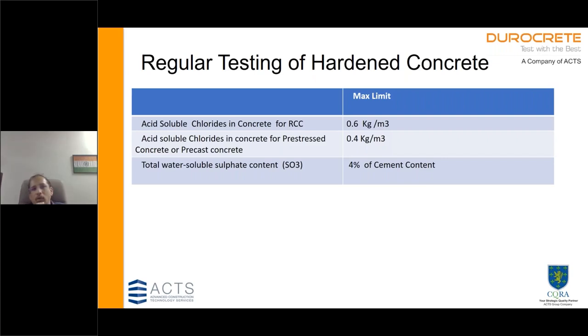One very interesting thing that happened about that Delhi collapse that I showed is that there are many buildings constructed 8 to 10 years back that have shown a lot of distress. And one of the reasons is the water that was used. It was found that treated water was used in Delhi, because of shortage of water, the local authorities allowed treated water to be used. Now, the treated water has to be tested for chlorides and sulfates and used. And probably the RMC plants were not having that control at that point of time. And that has resulted in a lot of corrosion related problems in the structures constructed during those times. So this is something that can easily tell you whether the chlorides and sulfates are within the permissible limits.